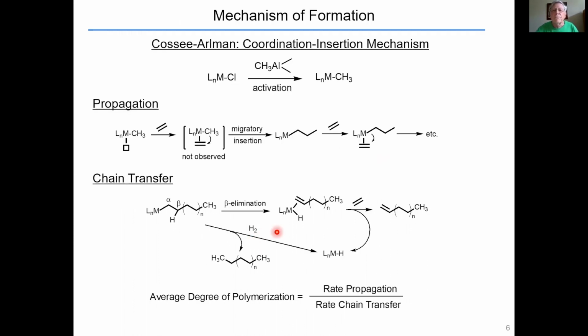The mechanism of polymer formation using early metal systems generally involves activation of some metal halide to generate a metal alkyl. And then the propagation step goes by a so-called Cossee-Arlman coordination insertion mechanism. So we generate some sort of metal alkyl, we bind ethylene, we do migratory insertion to build up the chain. This new metal alkyl binds another ethylene, another insertion, and so on, and we grow a chain. The resting state in these systems is the metal alkyl. The alkyl olefin species is never observed.